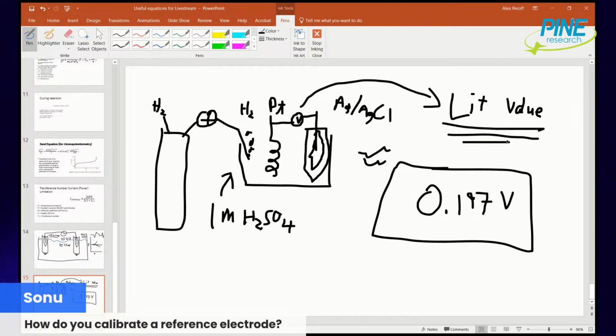So in this case, I had to take two dissimilar reference electrodes, take the open circuit potential between them, and make sure that they match the literature value of what that potential should be. That's how I knew. And once I knew that, I knew that my, quote, system was calibrated. If this was off significantly, well, I can't do very much with sulfuric acid and hydrogen gas and platinum. Maybe I could do some stuff with platinum, but I was pretty sure this was accurate. The silver chloride was the one that I thought had the higher likelihood of giving me a problem.